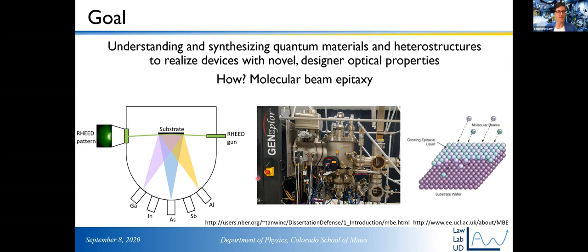So on the left here, you can see a little cartoon that I drew of the MBE chamber. Basically, in the chamber, and this is an actual photograph of one of our MBE systems, in the chamber is ultra high vacuum. So the pressure inside the chamber is about 10 to the minus 10 torr, right? Atmospheric pressure is 760 torr. So we're something like 1/1,000,000,000th atmospheric pressure. It's about the same vacuum as the International Space Station. The vacuum inside the MBE is extremely good.